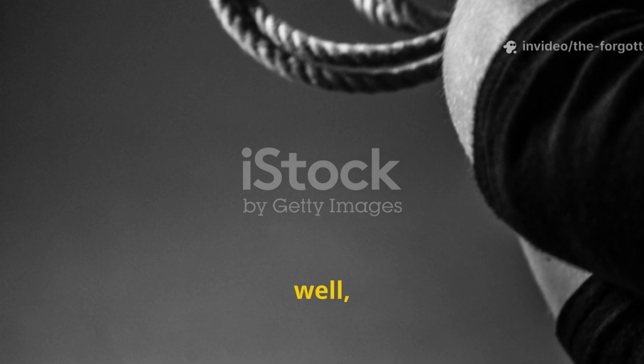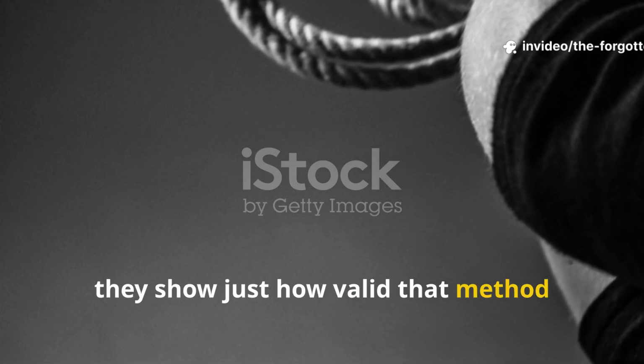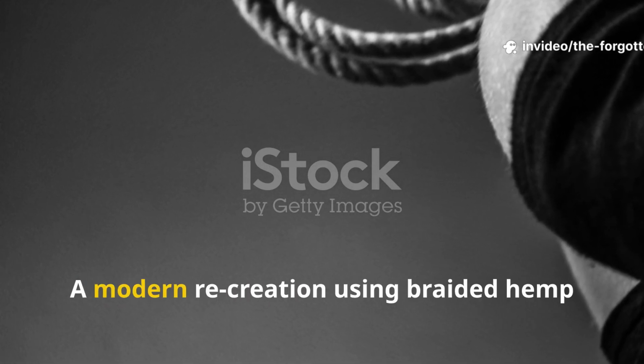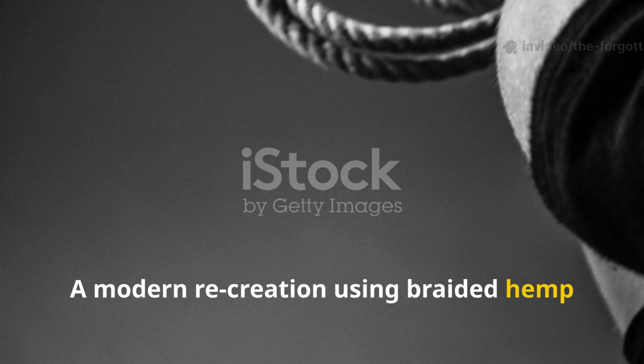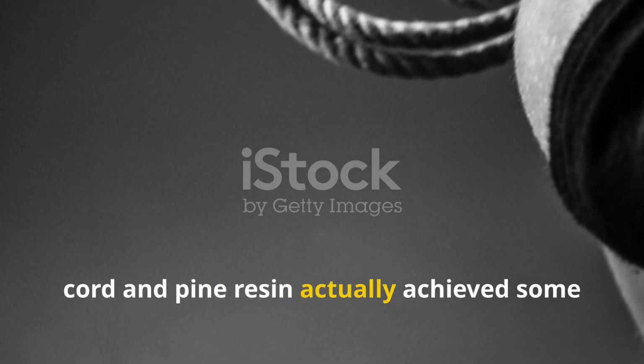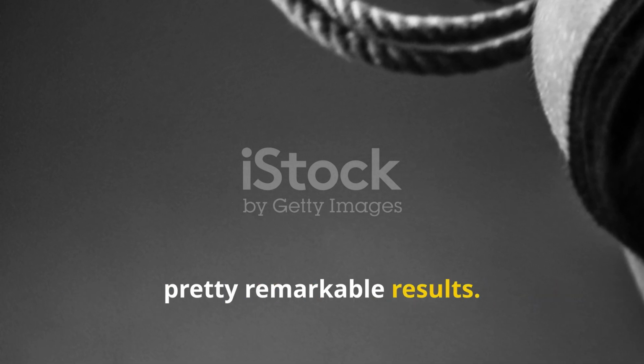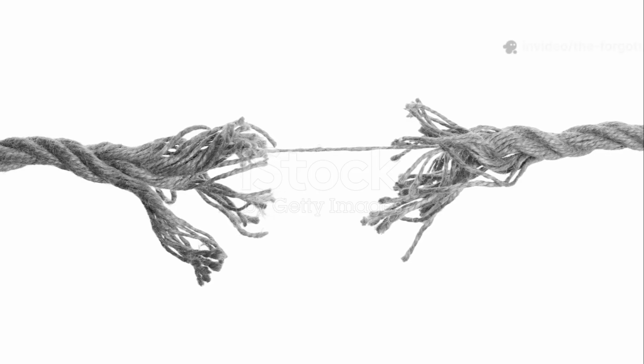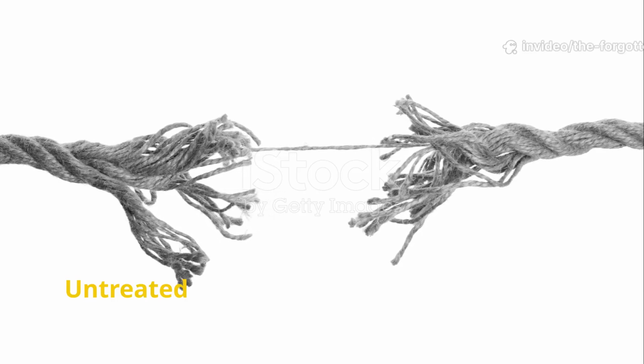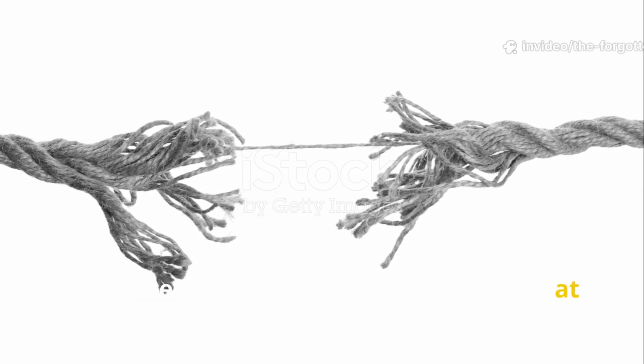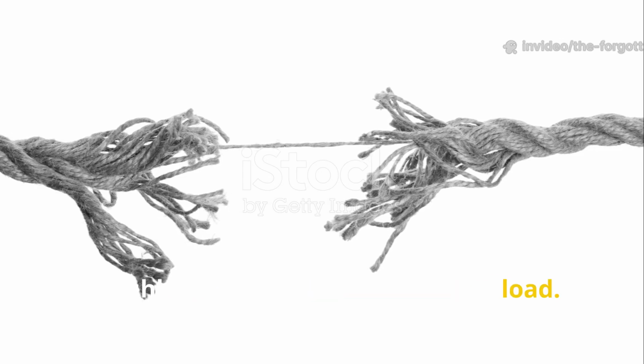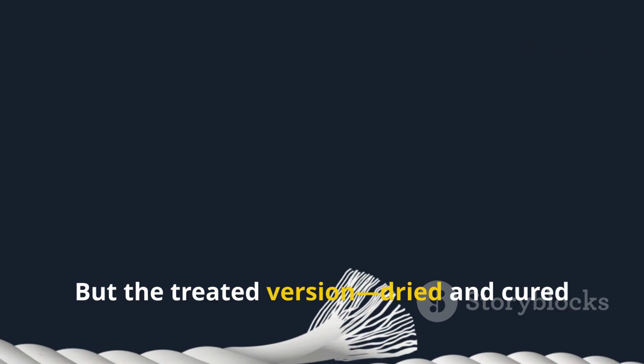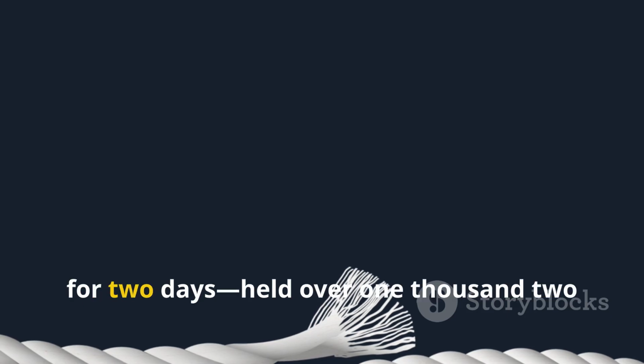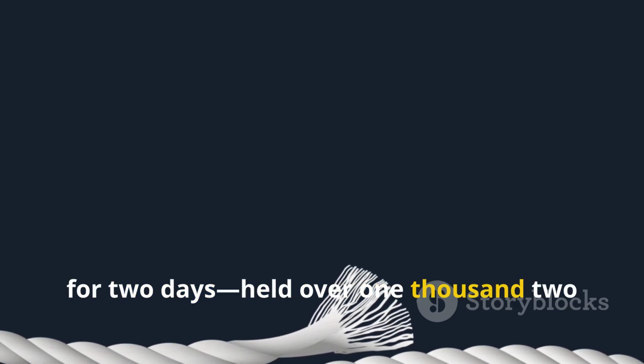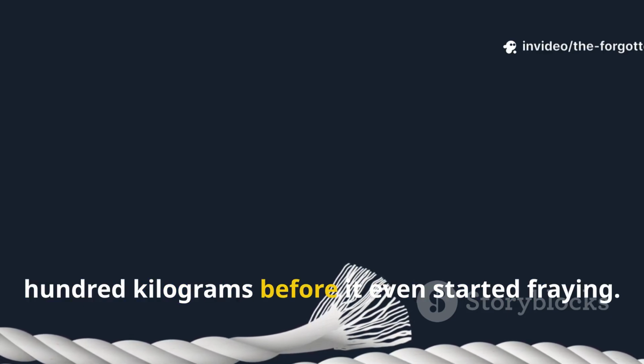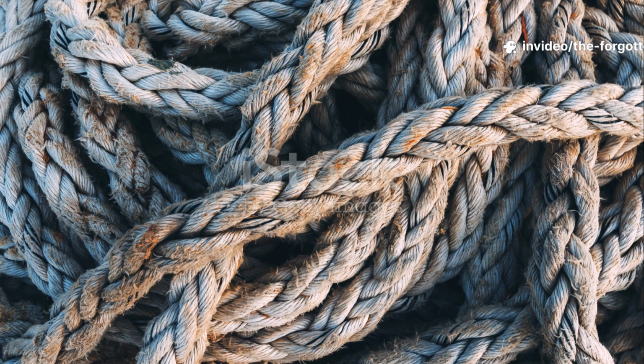Tests today show just how valid that method really was. A modern recreation using braided hemp cord and pine resin achieved some pretty remarkable results. Untreated hemp snapped under tension at roughly 500 kilograms of load, but the treated version, dried and cured for 2 days, held over 1,200 kilograms before it even started fraying.